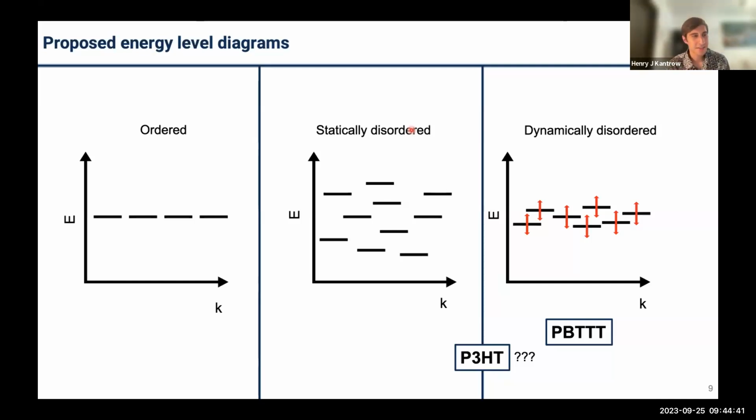You mean to use this as opposed to a crystalline polymer, something that is also very one phase? Yeah, you get something that seems to be much more crystalline, with much less of the amorphous regions, we thought, when you do the solid state processing. Yeah, certainly. In that case, you would probably produce something that is the most crystalline that you would get, though it's never going to be fully crystalline, versus something that's solution processed. So yeah, that's a good point, actually.